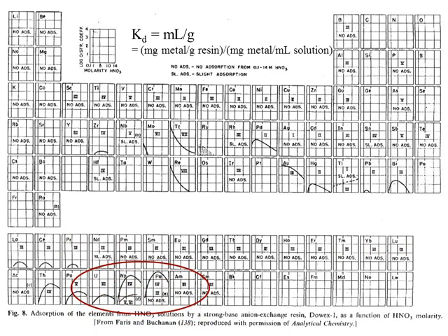For the actinides we see sorption that peaks and decreases. Plutonium-4 has strong sorption, plutonium-3 has no sorption, neptunium-4 strong sorption, neptunium-5 and neptunium-6 limited, uranium-6 not as much as plutonium. So the tetravalents here seem to be strongly sorbed, whereas the others are